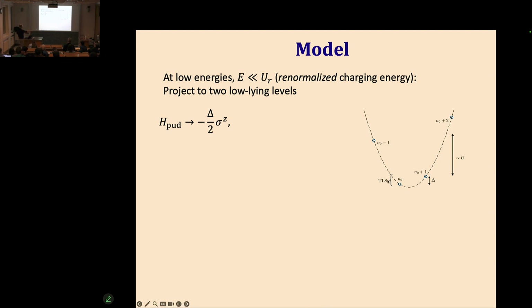If we go to low enough energies, and the superconducting puddle has a finite charging energy, we can project out all the energy levels of this island except for the two lowest energy levels, that have n and n plus 1 electrons. Depending on this parameter delta that can vary between one puddle and the other, these two levels can be degenerate with each other. So suppose there's some distribution of this random parameter delta, we'll get a probability distribution for the splitting between the two lowest energy levels of this dot. So we can describe this island by a two-level system, focusing only on the two lowest energy levels.